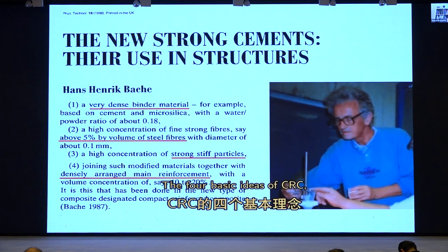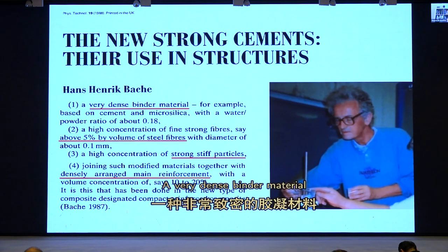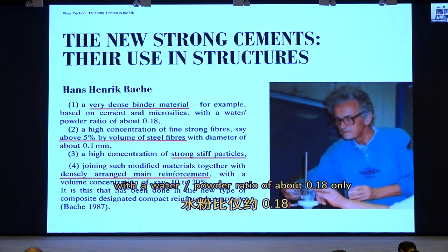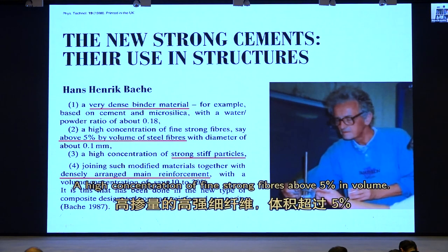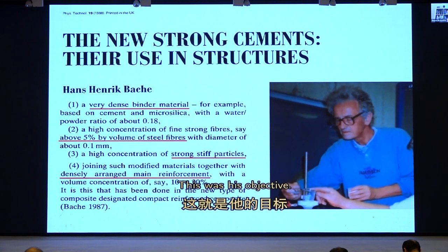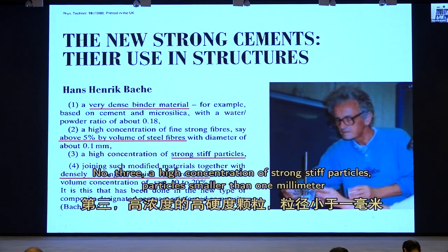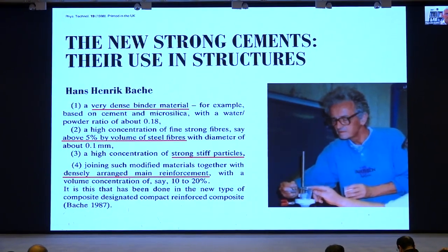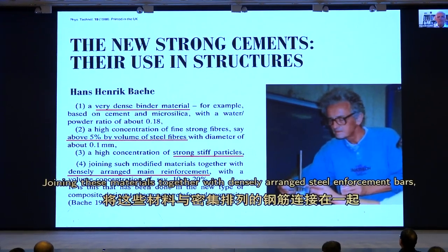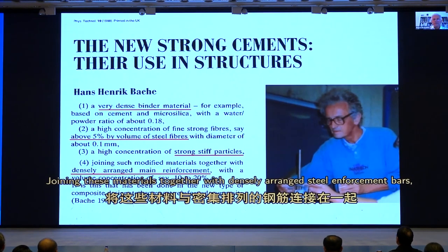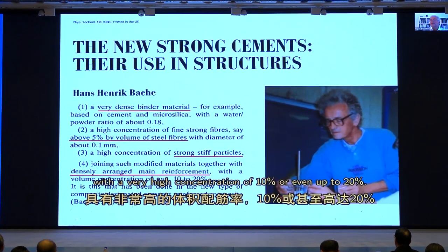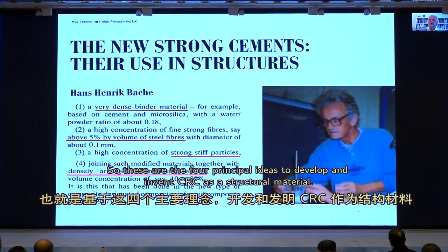The four basic ideas of CRC: a very dense binder material with a water powder ratio of about 0.18 only; a high concentration of fine, strong fibers, above 5% in volume, this was his objective; number three, a high concentration of strong, stiff particles, particles smaller than 1 millimeter; and number four, joining these materials together with densely arranged steel reinforcement bars with a very high concentration of 10 or even up to 20%. So these are the four principal ideas to develop and invent CRC as a structural material.